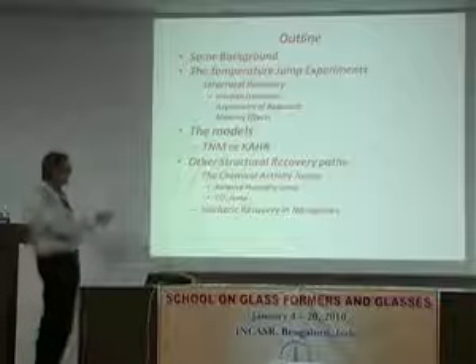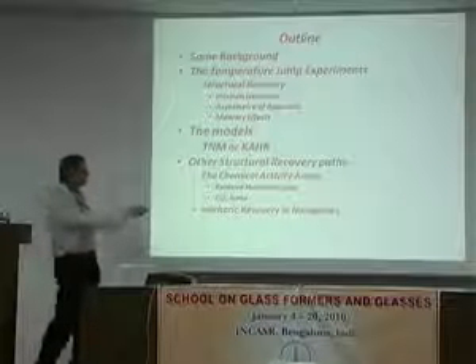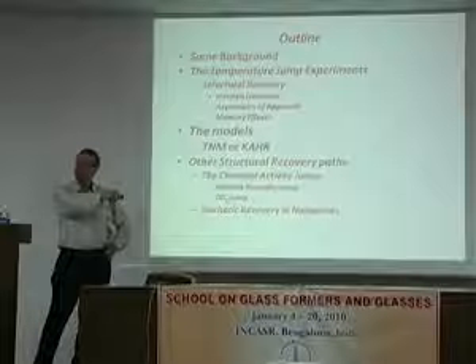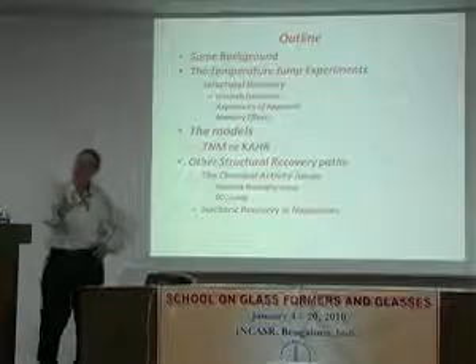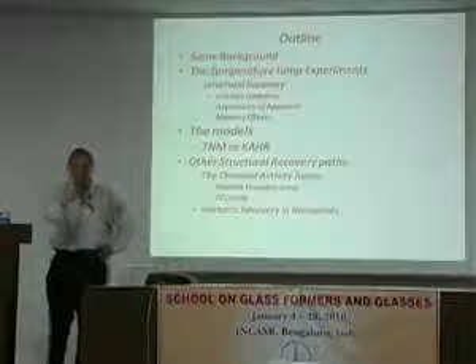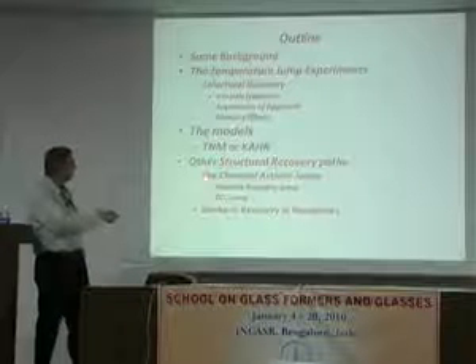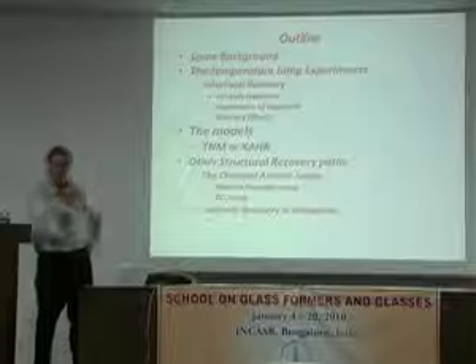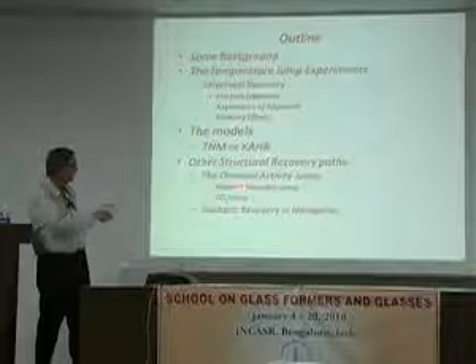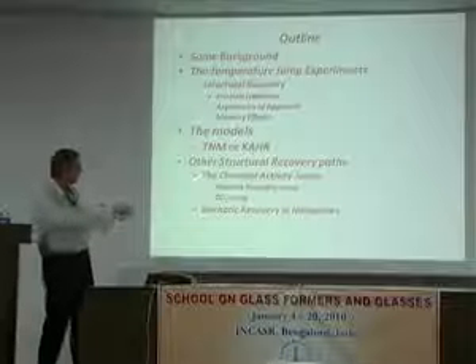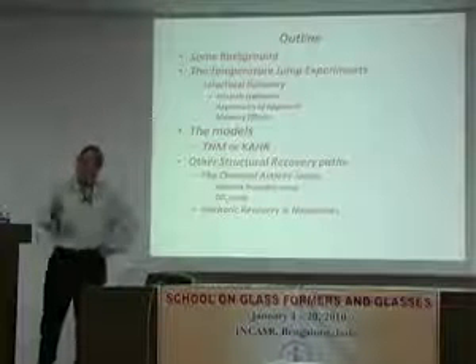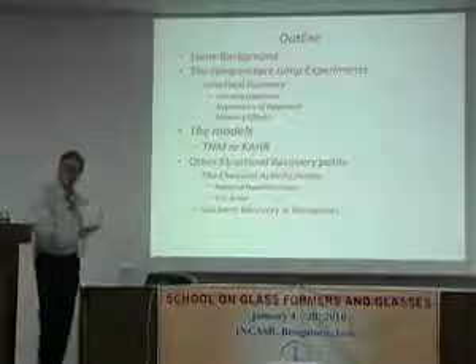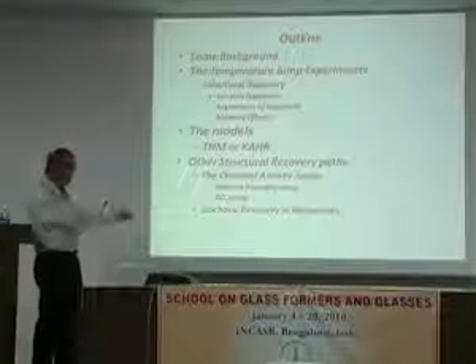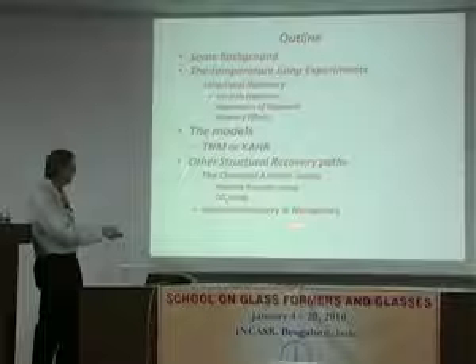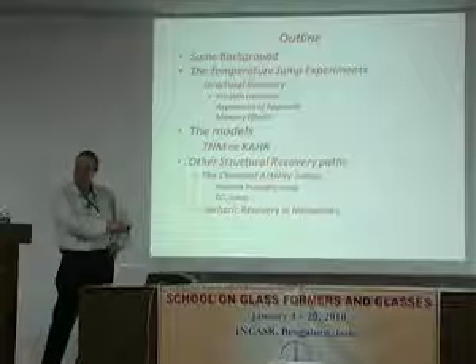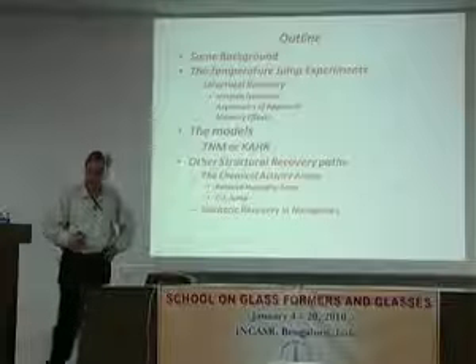And then, after I do that, I'm going to talk about some maybe anomalous results that are worth thinking about, where because polymers provide a certain kind of versatility to do experiments, it turns out we were able to do chemical activity jumps, meaning changing concentration of plasticizer, either relative humidity or carbon dioxide, and watch the behavior in a way that shows some surprising results about the glass transition itself, or the glassy state itself. And then I'm also going to talk about how well these models describe the actual structural recovery of a material confined in nanopores. Okay?